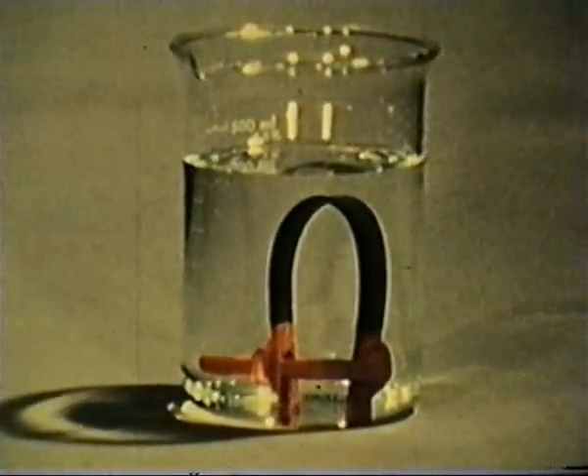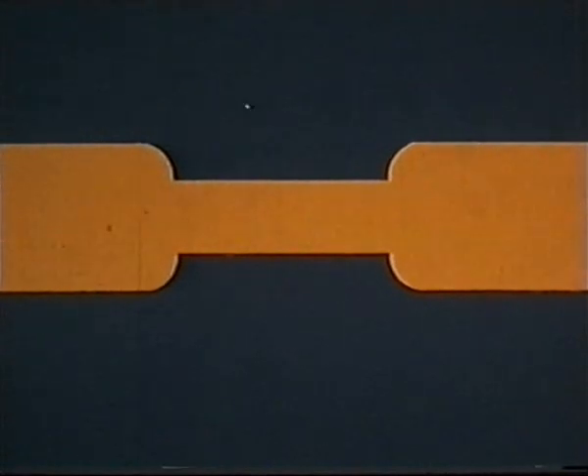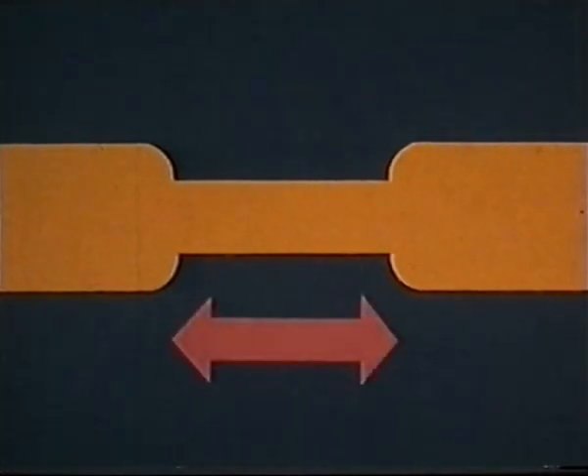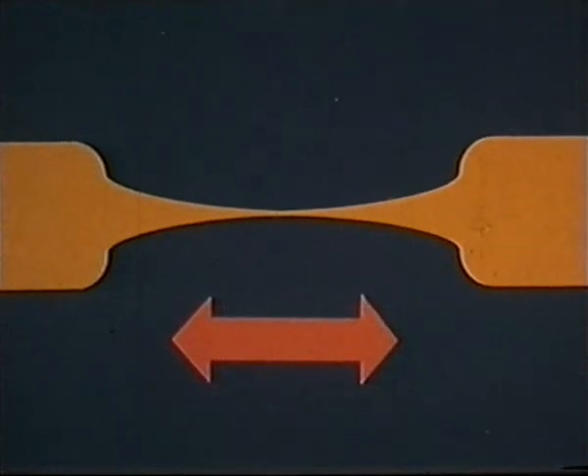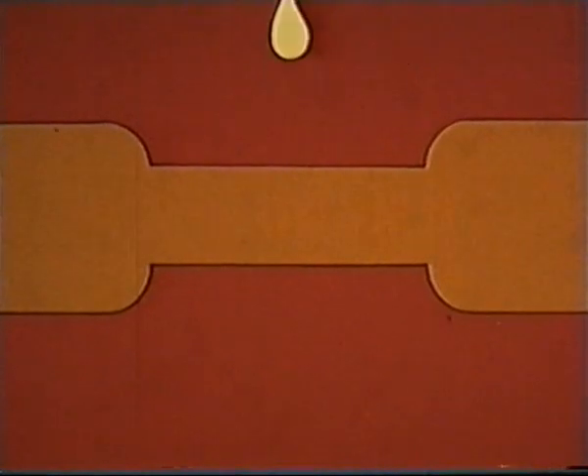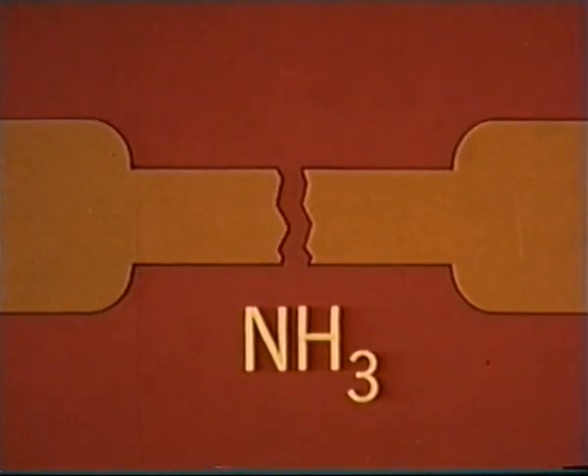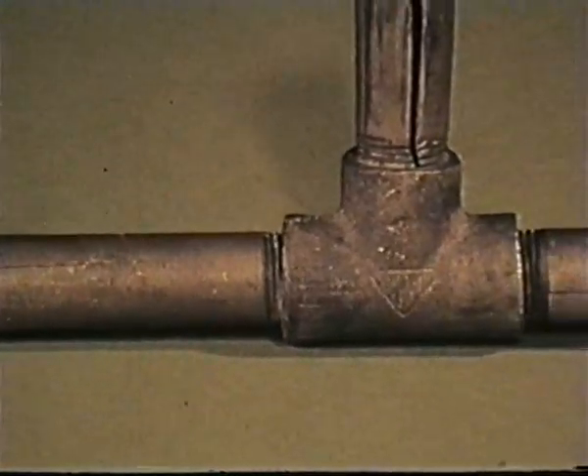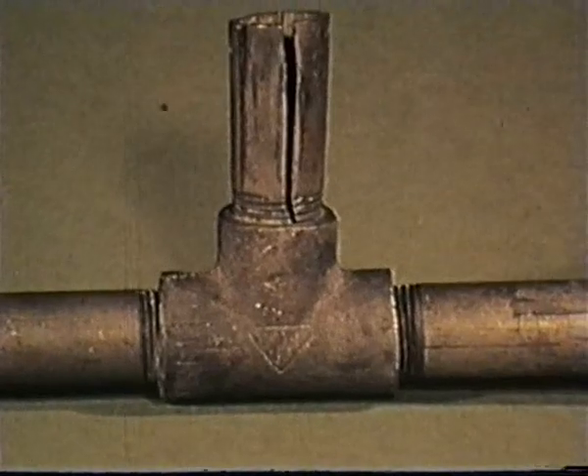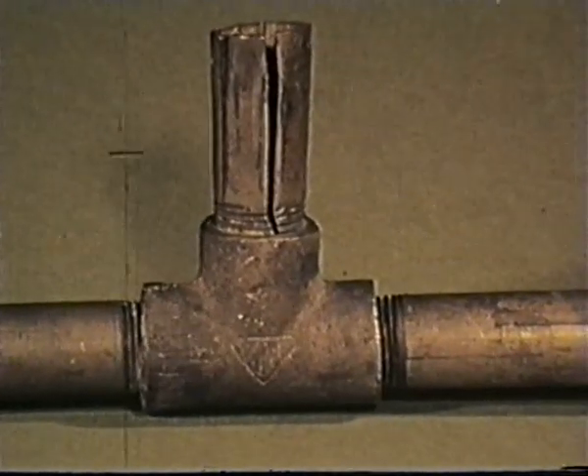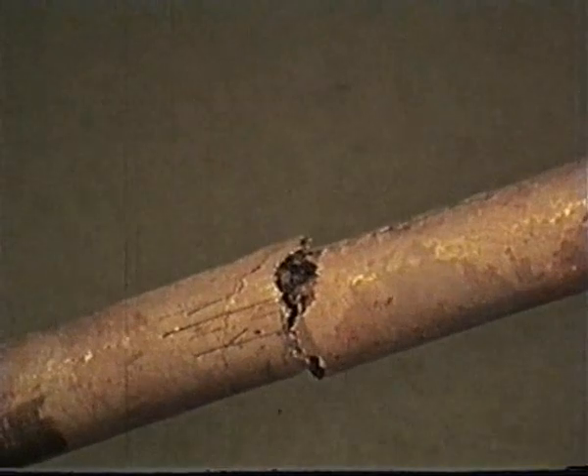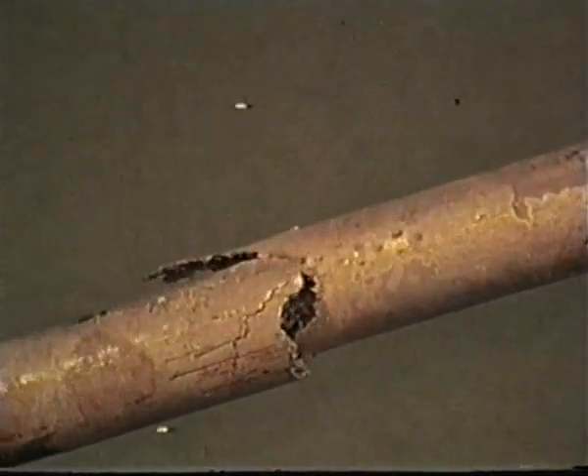The phenomenon of stress corrosion cracking is one of the most serious materials problems faced by industry. It is perhaps best described as the brittle failure of a normally ductile alloy at tensile stresses well below the ultimate strength of the metal in a specific environment. For example, the common copper-zinc brass alloys can crack if small quantities of ammonia are introduced into the environment. Other examples of this destructive mode are the cracking of austenitic stainless steels in chloride-containing environments and of carbon steels in nitrate, cyanide, and strong caustic solutions.